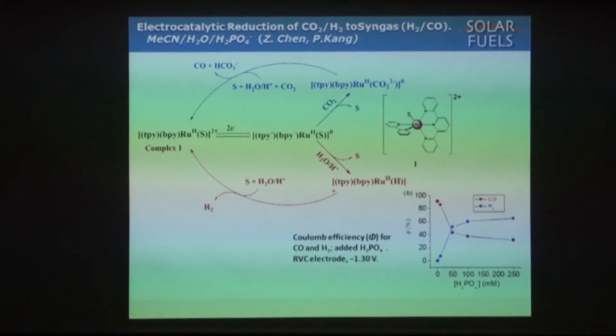First studies were done with acetonitrile, and what we showed was that if you look at this electrochemically, you first reduce terpy, you then reduce bipy, and when you do that with added carbon dioxide, you do get reduction of CO2 to CO. The mechanism involves dissociative loss of the solvent. It picks up a CO2. The electrons transfer from the ligands to make a carboxylic acid bound to the complex, this metallocarboxylic complex, which then in the end reacts with the CO2, pulls off an oxide, and CO comes out.